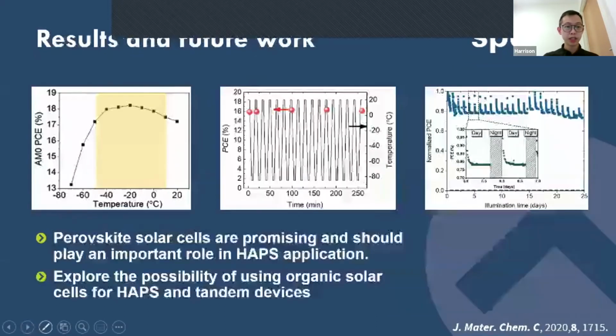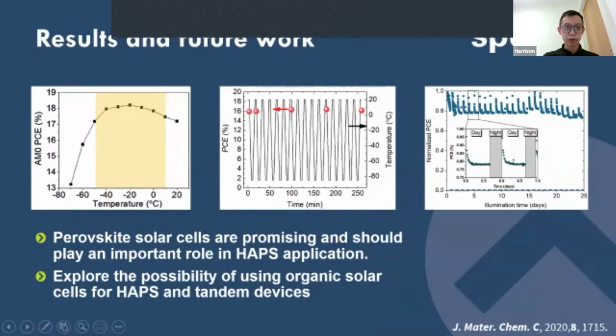So here is the data. Surprisingly, at room temperature or 20 degrees Celsius, the performance wasn't the best. What we find is that when we cool it down to a lower temperature, the performance is maximum at around -20 degrees, which is very nice because in HAPS conditions, we are not always operating at close to 20 degrees. Instead, we operate at a rather low temperature, between 0 and maybe -20, for the operational temperature. So this is a good sign for using this perovskite for HAPS application.